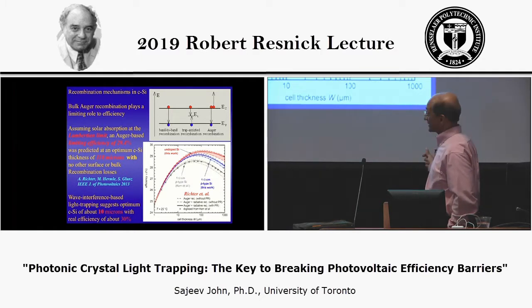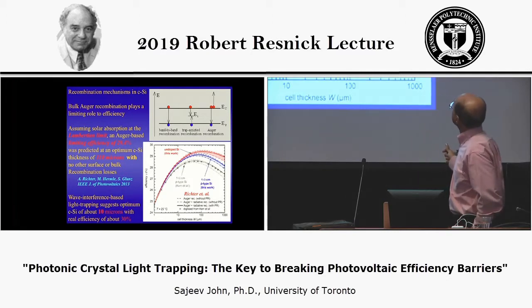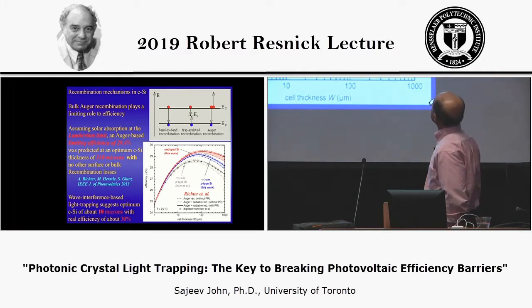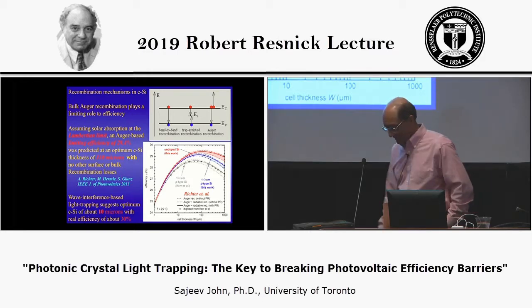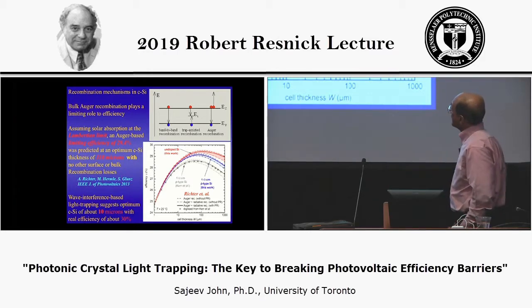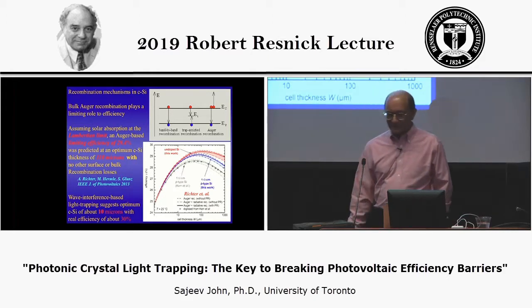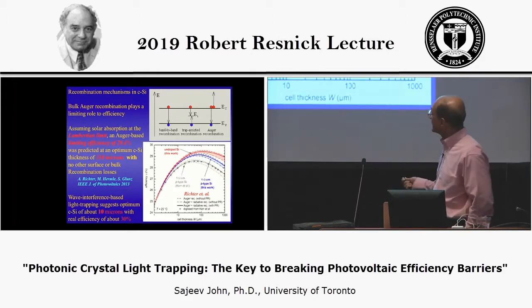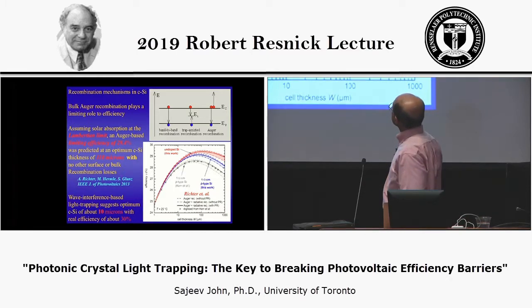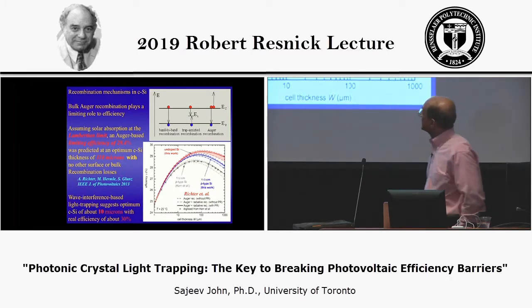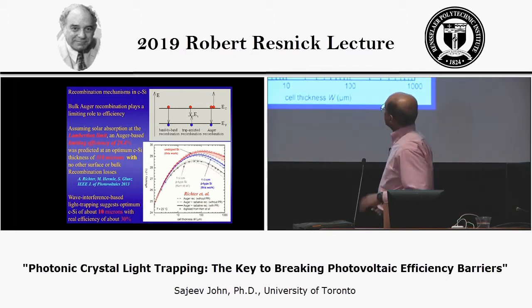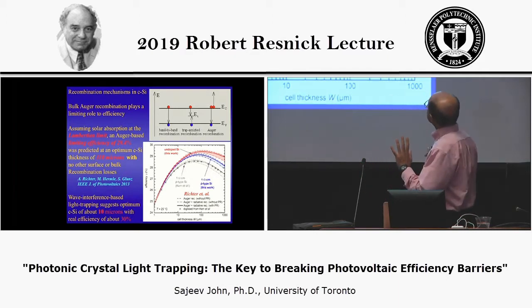A very significant one is what is called Auger recombination, where an electron-hole pair recombines, rather than emitting light, which would be rather difficult in this case due to the indirect band gap. It actually excites another electron higher up in the conduction band, and then that thermally relaxes, so the energy is just dissipated in terms of heat. And at the Fraunhofer Institute in Germany, which is sort of the European equivalent of NREL, they defined a model for these recombination processes where they mainly consider, in this case, just the Auger recombination.